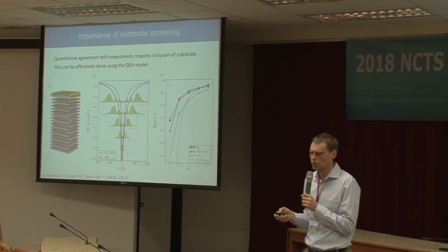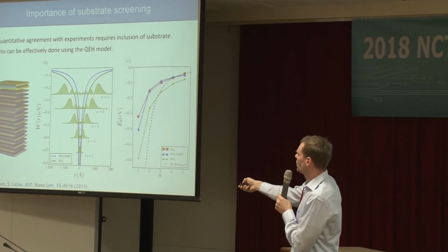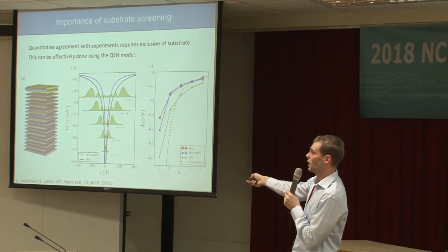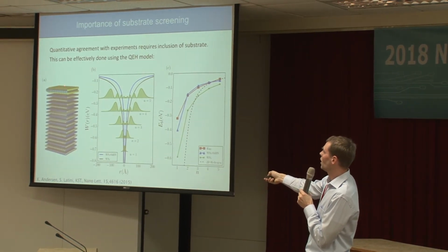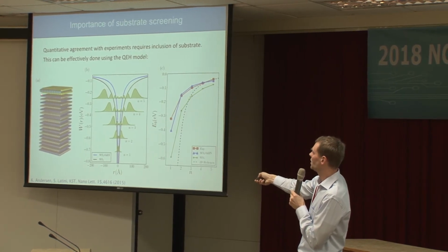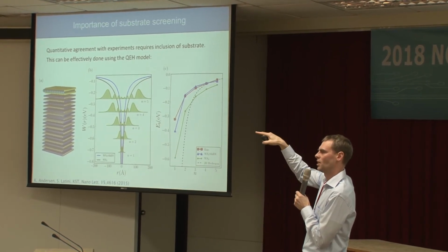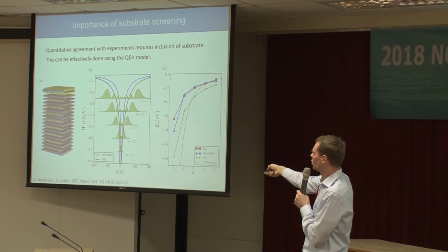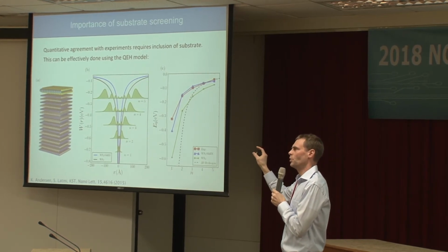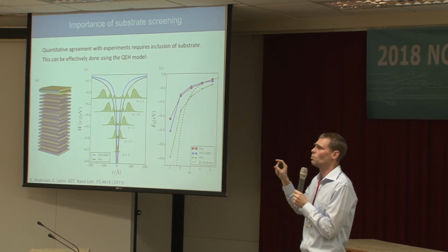So you get how many layers? Of course it depends, because the electron-hole interaction depends on Q if you go to reciprocal space, and the small Q values will have components that go way down here, so the potentials fall off as an exponential, e to the minus Q times Z. So for small Q, this is going to be long-ranged. But I think just 3, 4 layers is okay to get the main effect.